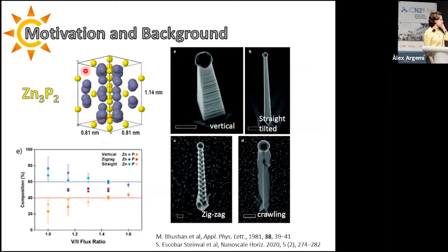But in these 40 years, the material growth methodology has improved. A couple of years ago, our collaborators at EPFL tried to obtain zinc phosphide on top of indium phosphide. They started growing it with vapor liquid solid growth, obtaining vertical nanowires. Depending on the flux ratio between the zinc and the phosphorus material, and the temperature of the substrate, they could tune the morphology from vertical, straight, tilted nanowires, to zigzag, and crawling. The most promising for photovoltaic application is the vertical nanowire.